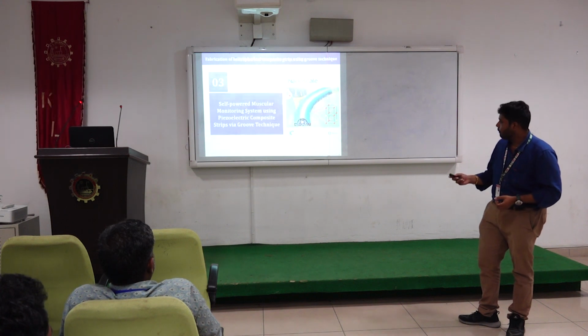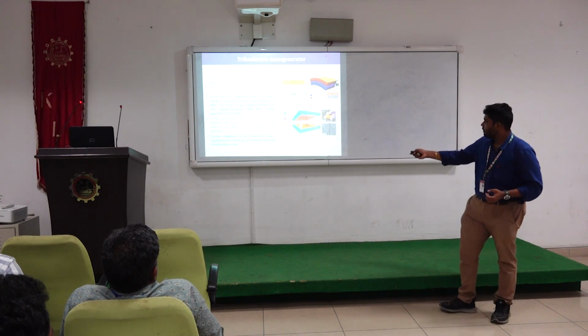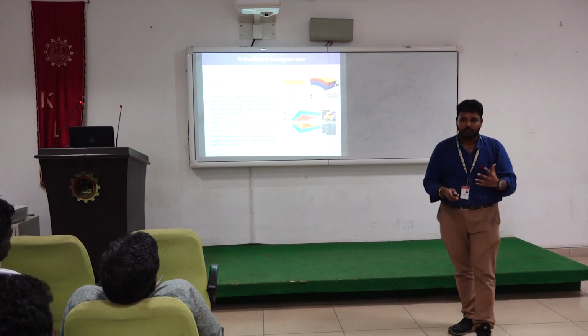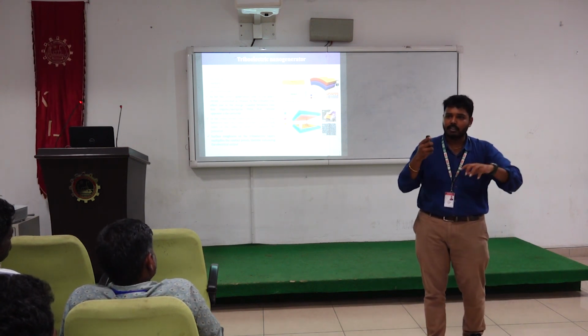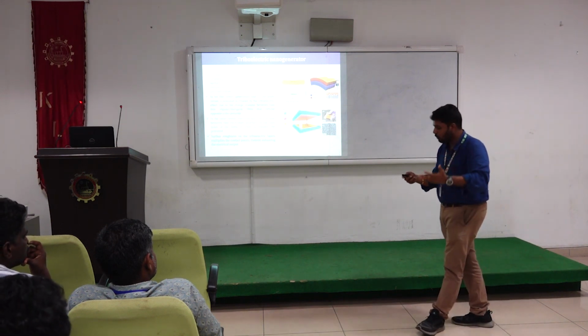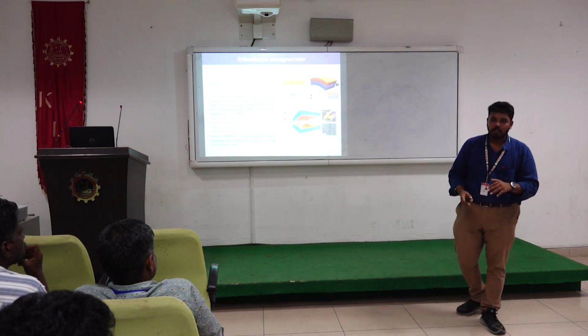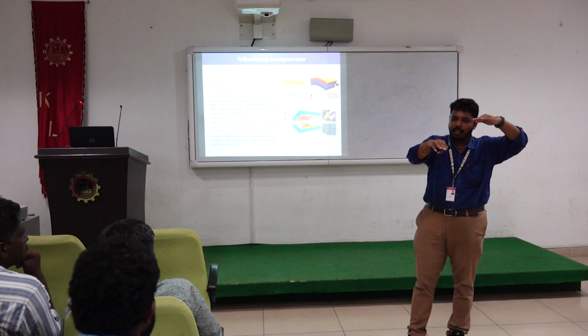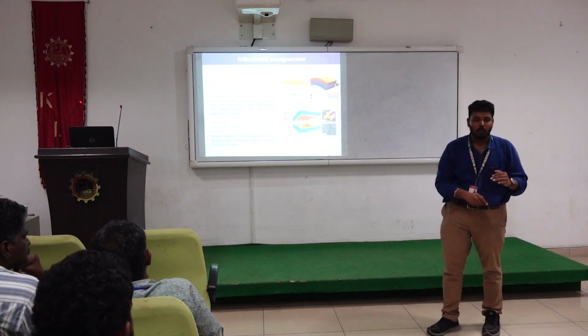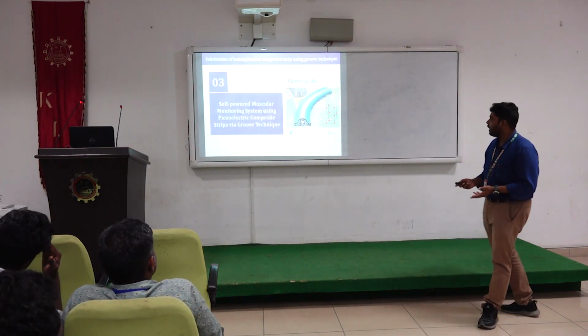Again, there is something called surface roughness here. Here you can see one surface is very flat, and the second surface has multiple roughness features. What this surface roughness does is enhance the contact points, thereby multiplying the electrical output you are producing. If the top is a flat surface and the bottom is a flat surface, that means only a single contact point will be there. When the surface roughness is more, the contact points multiply, thereby improving the electrical output.